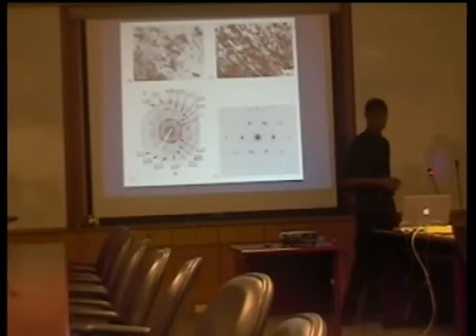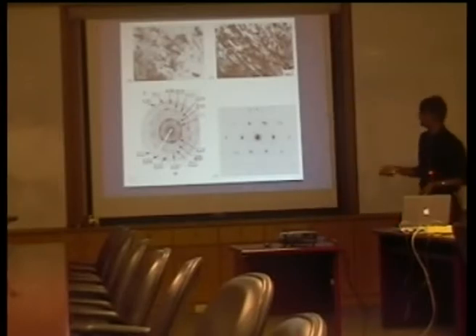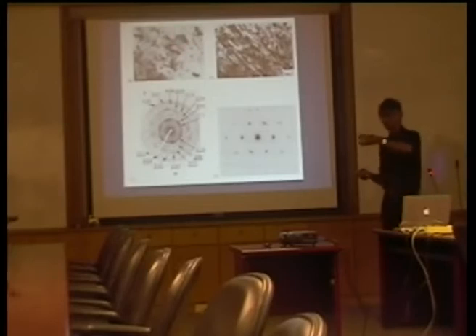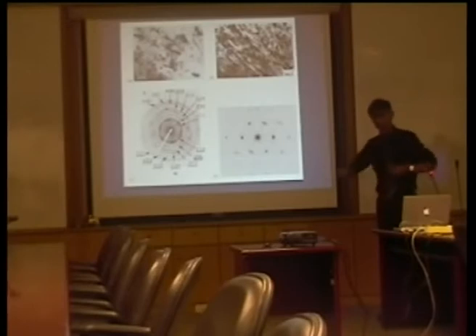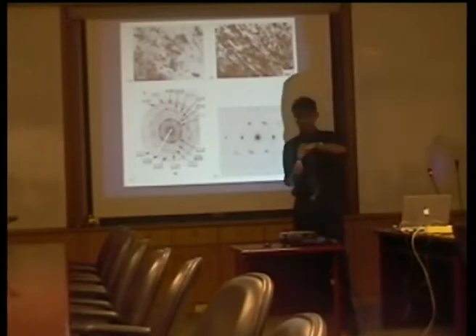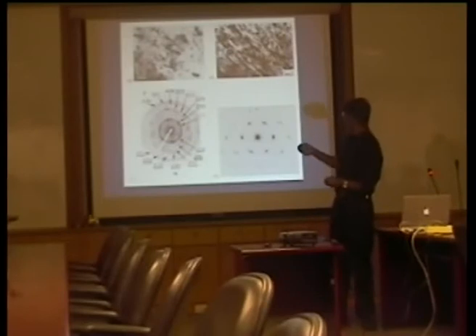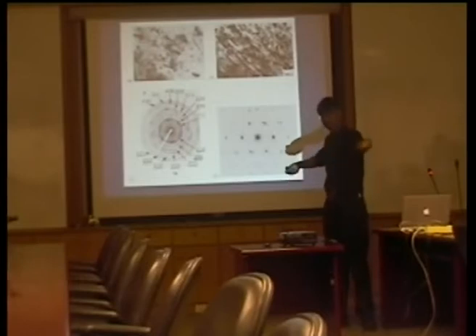And this is what it looks like after very severe deformation. So this is the transverse section where you see almost equiaxed grains. But when you look in the longitudinal section, we see very severely deformed grains. So in three dimensions, this is like cylinders which are packed together. Okay? Because look, this is the cross section and this is the longitudinal section. The deformation has made these into very, very long cylinders which fill space.